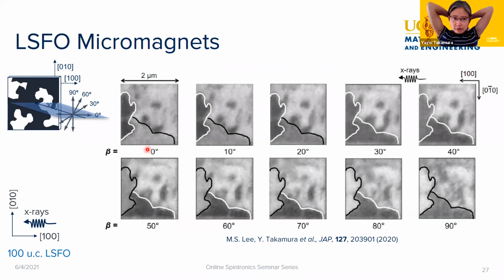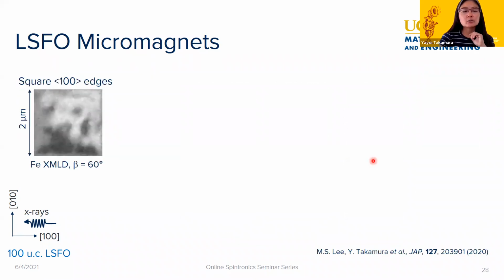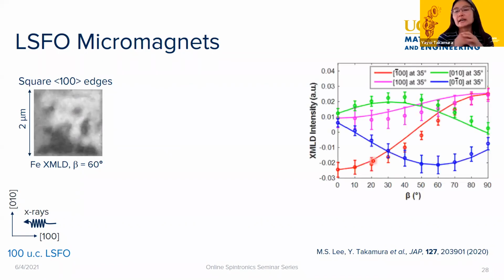So the first thing I want to show you is a thick film. This is analogous to the last example, where we have 100 unit cells of LSFO, an antiferromagnetic material, and then we pattern it again into 2 micron squares. And again, this is the series of images that we get as we do this polarization rotation series. And so we get a series of different types of domains, which all have their own beta dependence, right? And so again, pixel by pixel, we can map the dependence of those domains, and we again end up binning them into 4 different types. So these are their dependence as a function of beta.